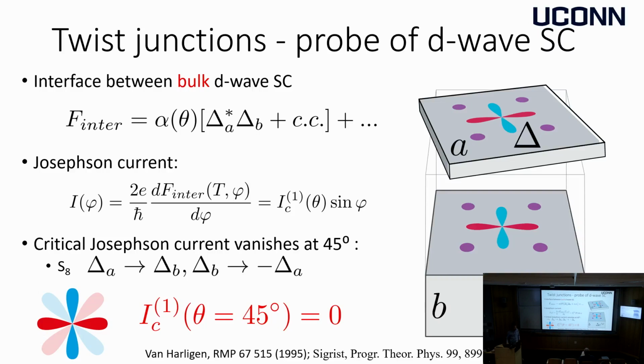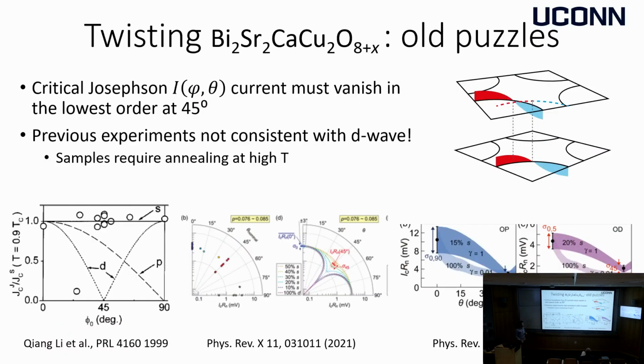So the experiments had been done already at that time, and the puzzle was that they were completely inconsistent with D-wave pairing. If you look here, that's one of the first systematic experiments. People measured the critical current as a function of twist angle on the junction, and you can see that most of the data points are completely independent of the twist angle, which is more consistent with something boring and uniform rather than with highly anisotropic D-wave pairing. Some newer experiments see a little bit more of a spread developing around the 45 degree angle. This axis is essentially the critical current.